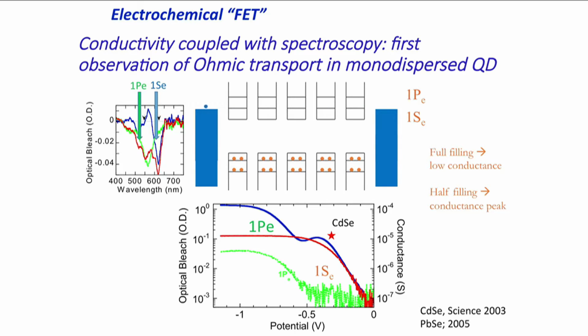And then what was particularly nice and expected, but very nice, is that when that level became full, and we could see this by the saturation of this optical bleach, the conductivity dropped. And so you expect that. You have 2 electrons per state. The state can only take 2 electrons. It's filled on the left, filled on the right. No matter how much you push or pull, the electrons can't move.